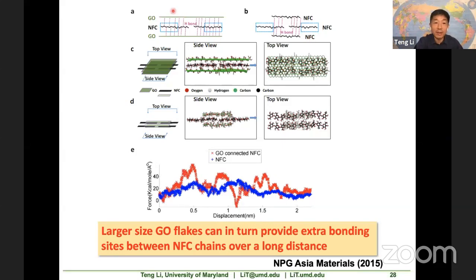And for this hybrid one, I want to make an analogy. You can imagine it's like you are using two pieces of pizza to sandwich a lot of spaghetti noodles, okay? Now, in this case, when the two spaghetti noodles are not interacting with each other anymore, they are still interacting with the pizza above and below. So in this case, the larger graphene oxide flakes can in turn provide extra bonding sites between the NFC chains over a much longer distance. So that's why the hybrid one is better than the pure NFC one.